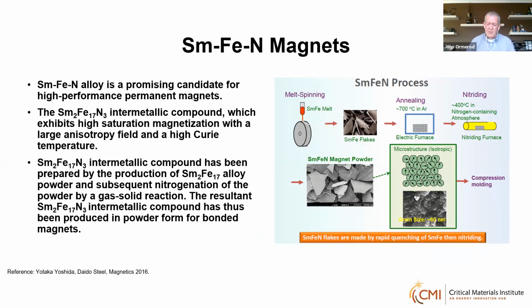Now, several companies claim to produce these powders and magnets on a commercial scale, but the big issue is the 2-17-3 compound is metastable and actually decomposes above about 550 degrees C. So fully dense magnets certainly aren't possible by sintering, and even hot pressing and hot forming cannot produce fully dense magnets of this compound.